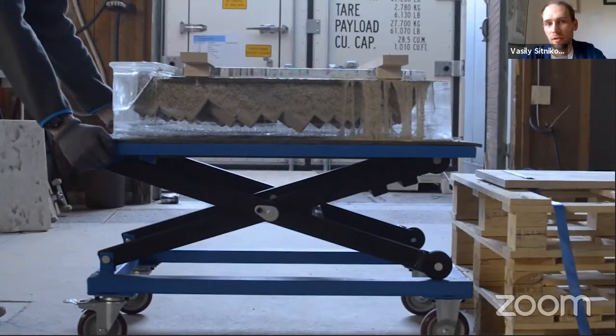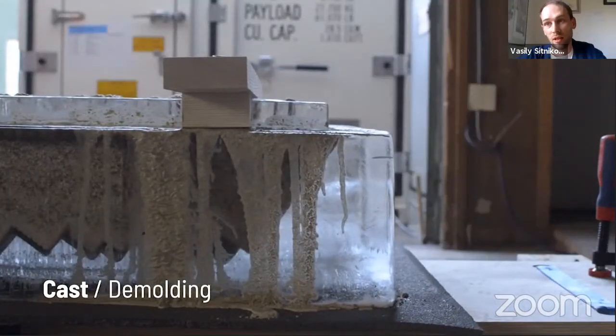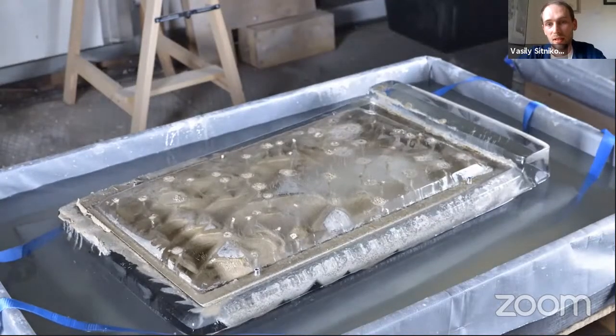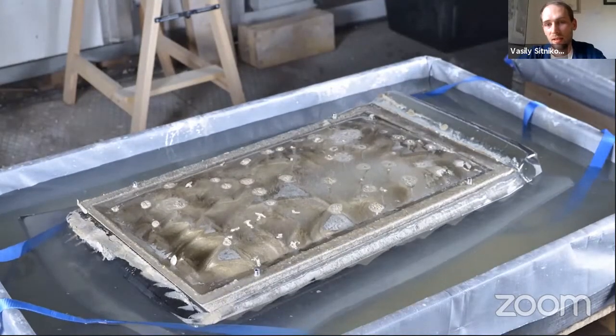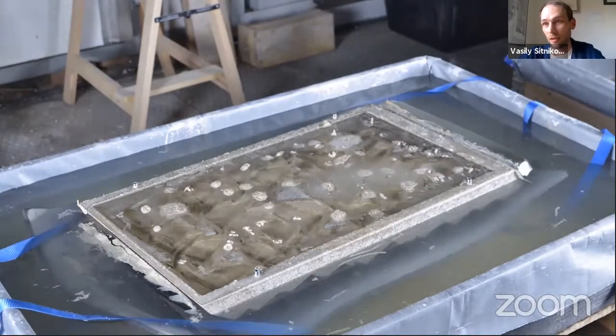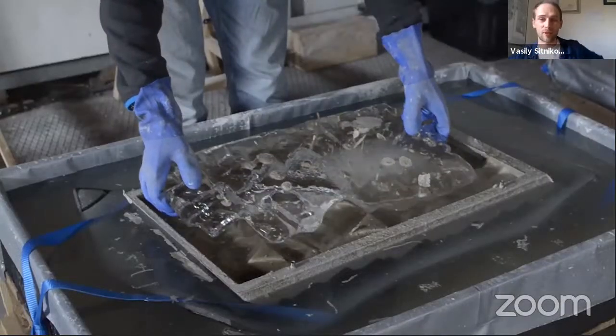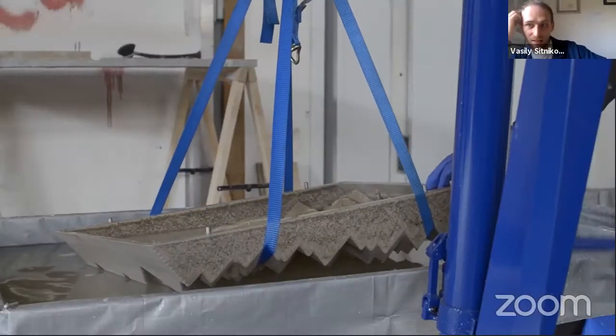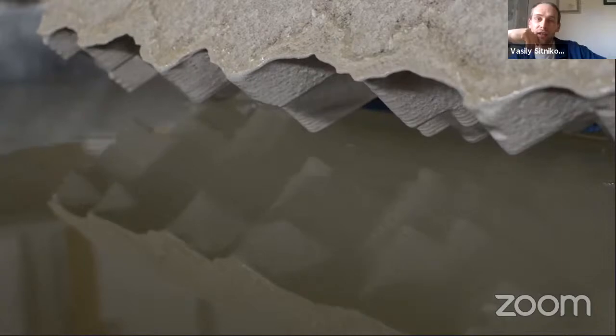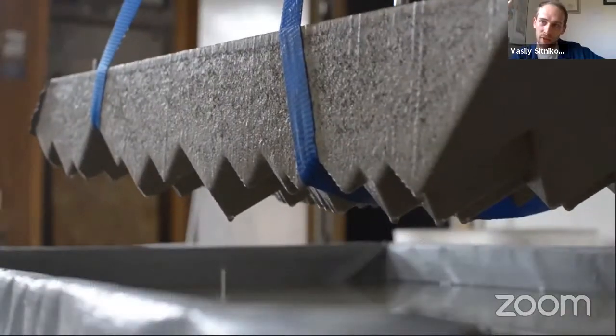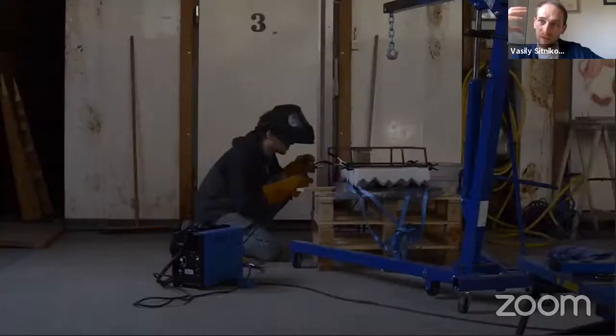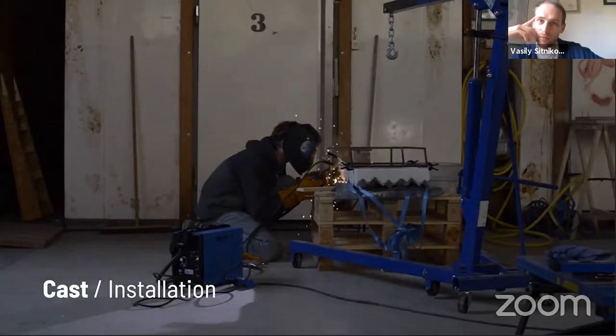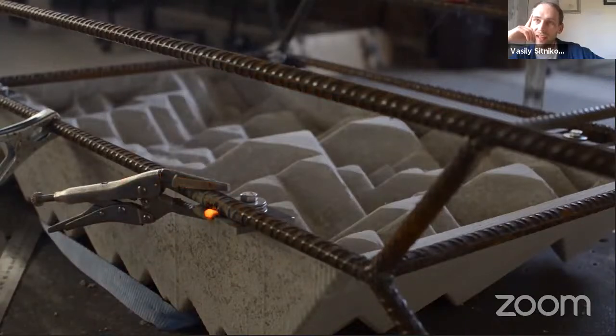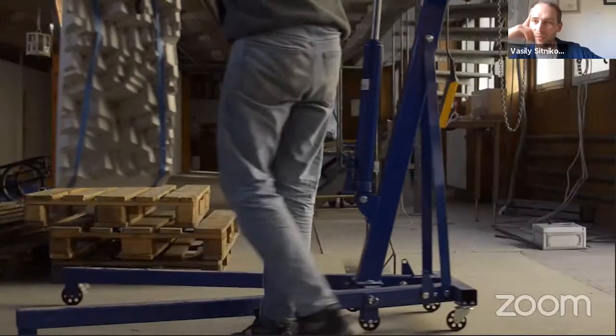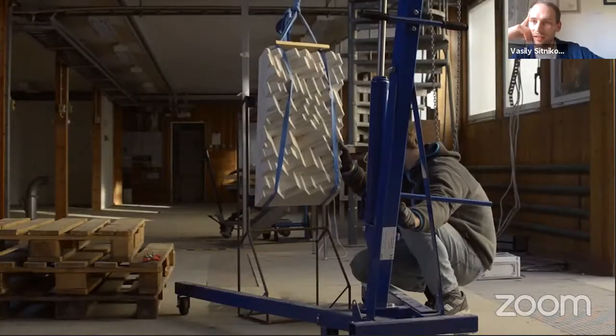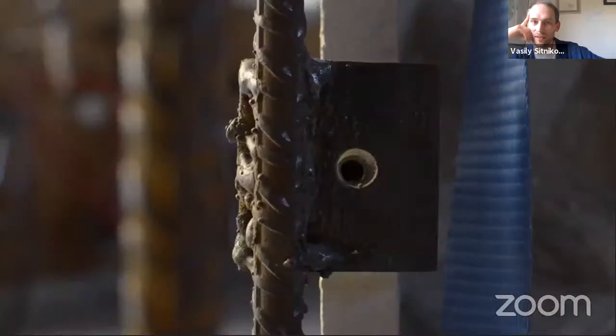So after casting, there is a process of demolding, which is, as I've mentioned, autonomous. This is the time when you can go out and have some nice beer in the park. So the element is kind of matured in water, which is very good for concrete in the early stage. There is no shrinkage, the dimensions are perfect. And then there is this imitation of a construction process with welding and installation on the steel framework on the back.